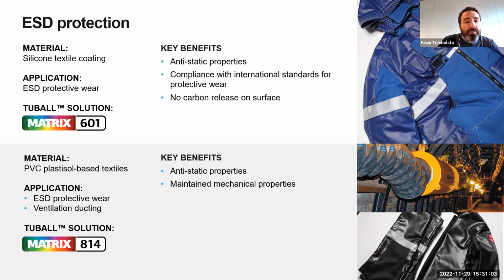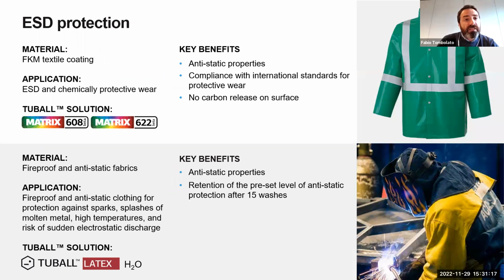ESD protective wear can be achieved combining the chemistry of PVC plastisol together with our Matrix 814 to achieve antistatic properties together with mechanical properties. This is a clear example of what a multifunctional fabric is. I mean, a system that brings together different properties. In this specific case, ESD protective properties were combined with chemical protective properties, combining the chemistry of FKM together with Matrix 608 and 622 Beta to achieve antistatic properties that are compliant with the international standard for protective wear.